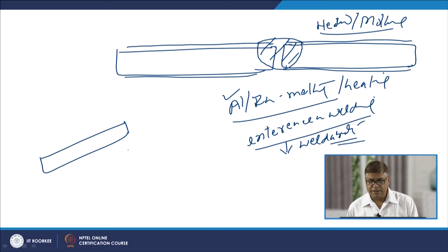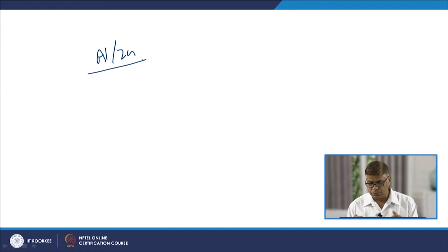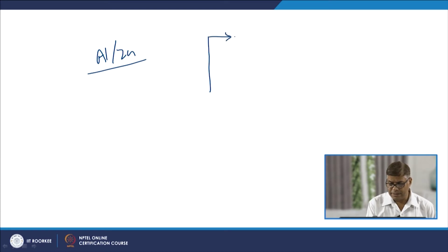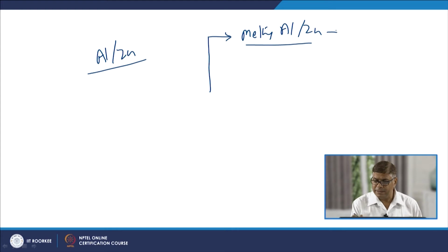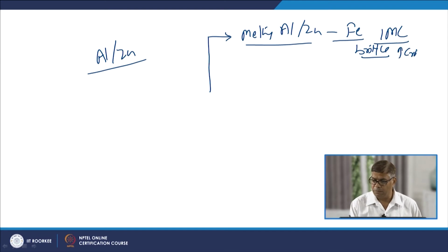So, what are the ways by which the aluminum or the zinc coating can interfere in welding and so as to reduce the weldability? Say these are the three different ways. One is that the melting of the aluminum or the zinc leads to its interaction with the iron to form the intermetallic compounds which are brittle, low strength and low ductility. So, these promote cracking.